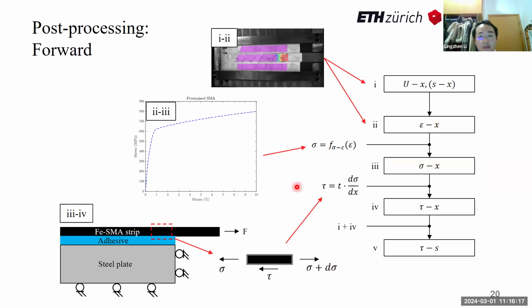During the DIC measurement, we have the full-field displacement measurement, which can be simplified to a one-dimensional displacement location behavior. Integrated in the DIC software, we can analyze the strain location behavior. Substitute the measured one-dimensional stress-strain behavior into this strain location behavior, and we have the simplified one-dimensional stress location behavior. And further analyzing the equilibrium of the shape memory alloy infinitesimal element, we can obtain the shear stress location behavior.